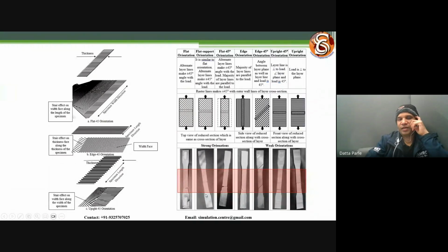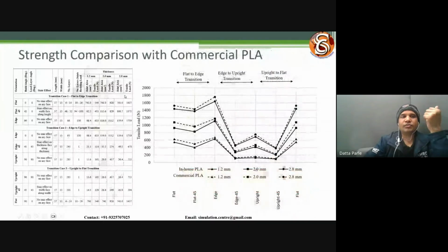If there is a stair effect, then it is an easy fracture. If there is no stair effect, then it was a stronger component and failed differently. That is what we checked, what is happening with the fracture, layer strain, layer area, and a lot of those analyses. How much is the joint area, what is the area of resistance, and how that is correlated. When we did this analysis, we tried validating it with the mechanics of the failure behavior.